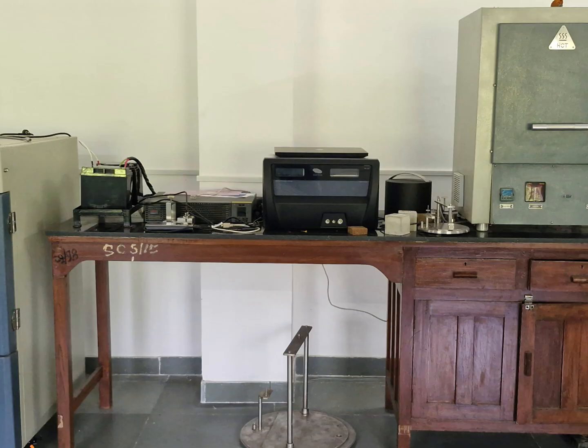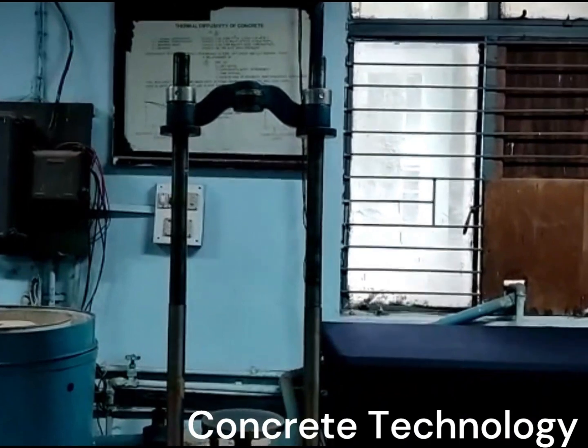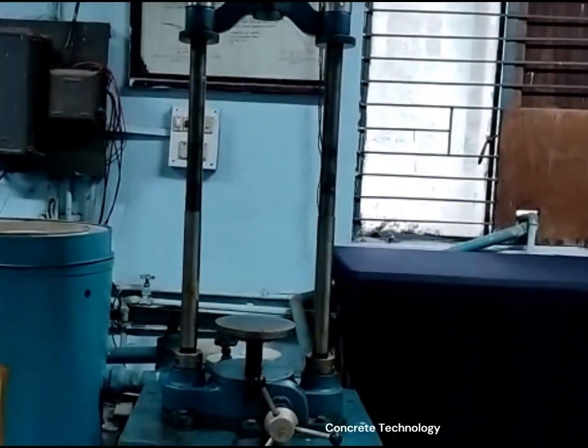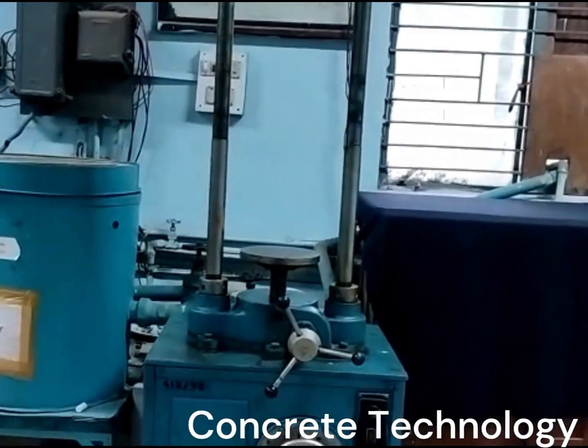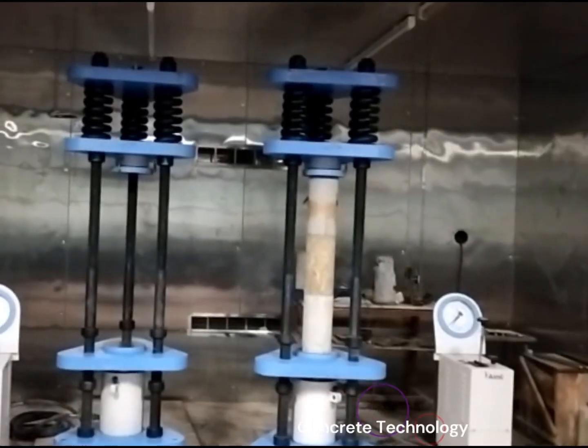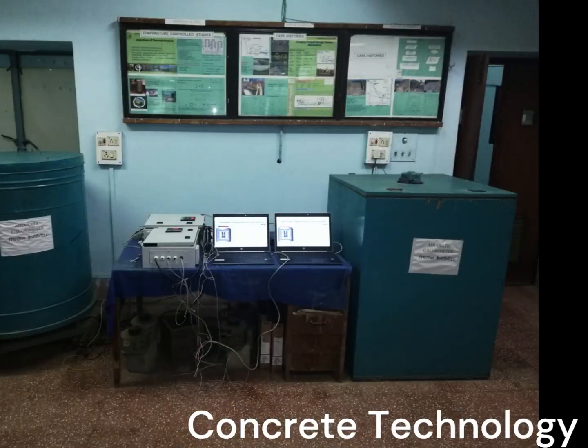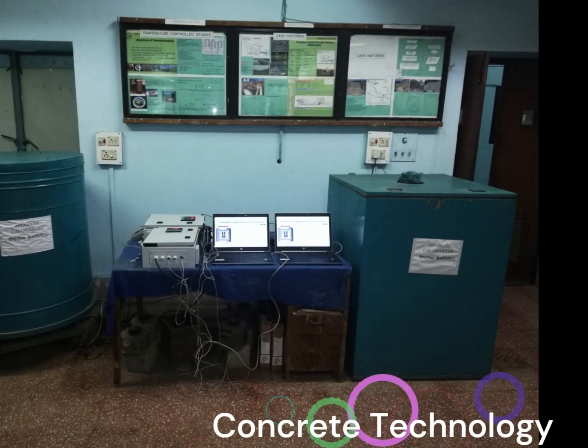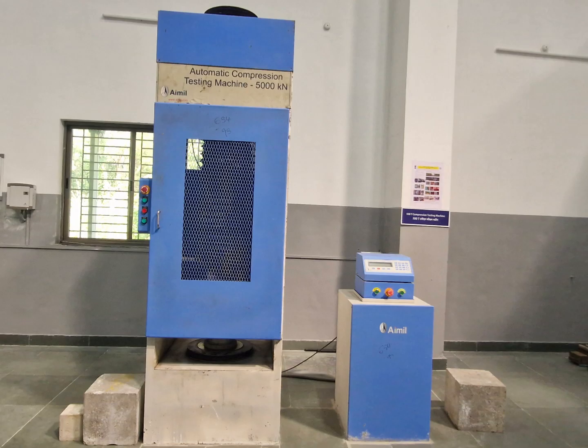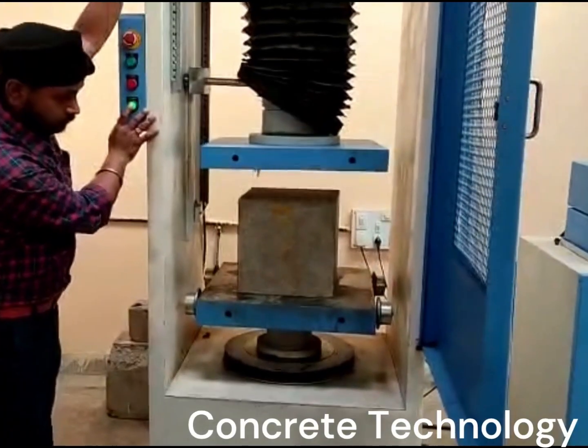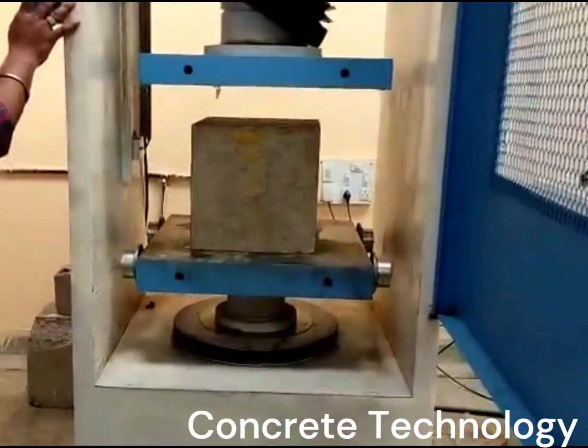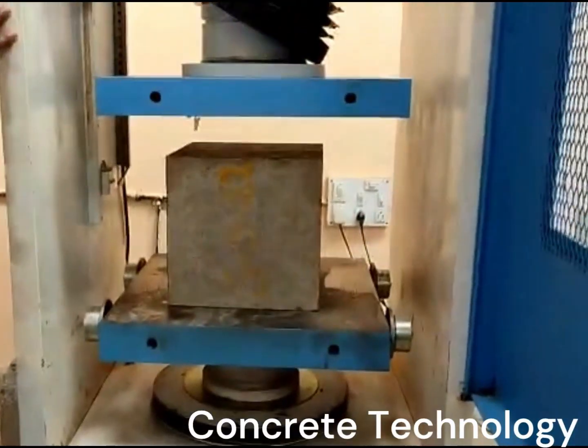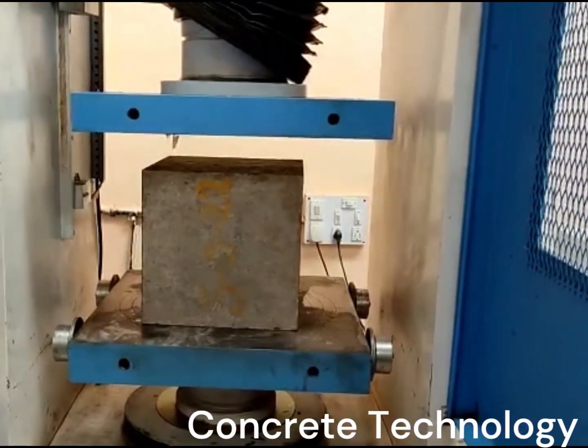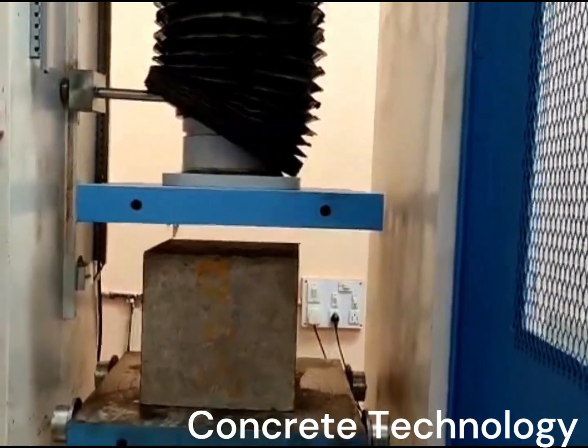At CWPRS, facilities have been developed for evaluation of temperature rise due to heat of hydration of cement and evaluation of diffusivity of concrete. Simultaneously, capability was developed to use these data to predict evaluation of temperature stresses taking due account of sustained stresses and creep of concrete. 1. 500-ton CTM. The digital automatic computer-controlled compression testing machine, 500T, 5000 kN capacity, is required for testing of concrete, masonry and repair materials of various large sample sizes under compression mode.